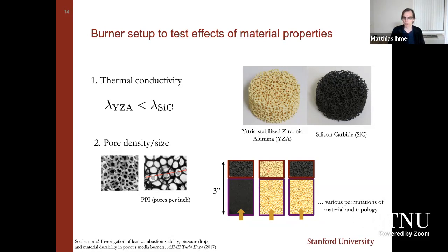To illustrate this, you can think about a very low thermal conductivity, as for instance illustrated in this zirconia material. You can imagine that this is a rather poor porous media burner, in the sense that we constrain our operability. If you have very favorable heat conduction, for instance utilizing silicon carbide, we can extend the operability of this burner.